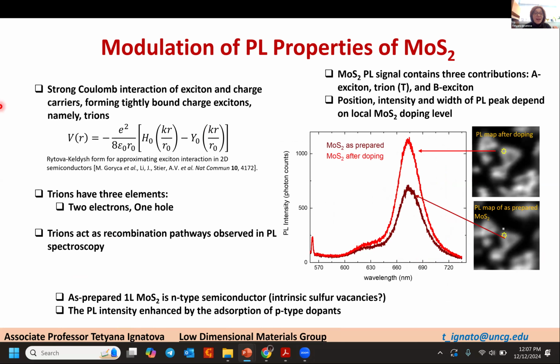Okay, here we are. You can see here 2 spectra. One is molybdenum disulfide as prepared, and the second one is molybdenum disulfide after we doped this material with a P-type organic molecule, and it was done immediately after growth. The photoluminescence peak had significantly changed, not only in intensity, but also in the shift of the photoluminescence maximum. So you can see that just by simple chemical doping, we can change photoluminescence and manipulate the band gap of molybdenum disulfide.